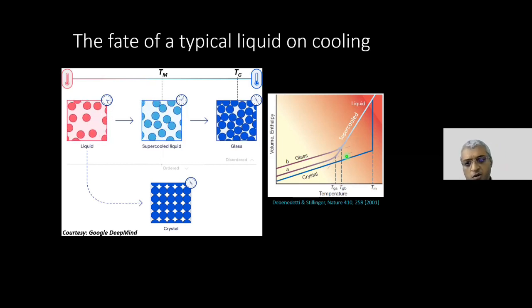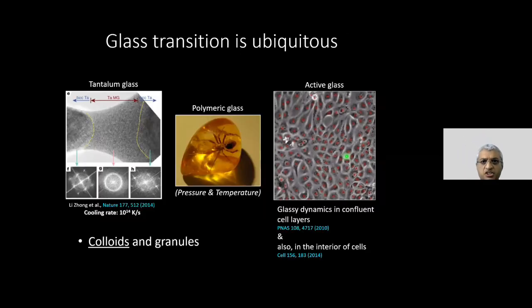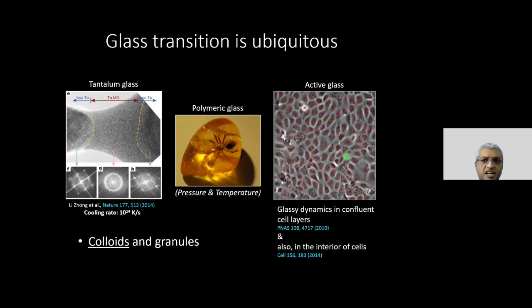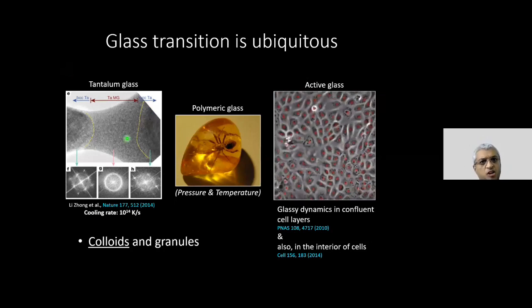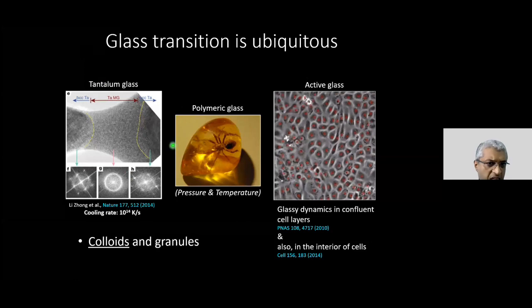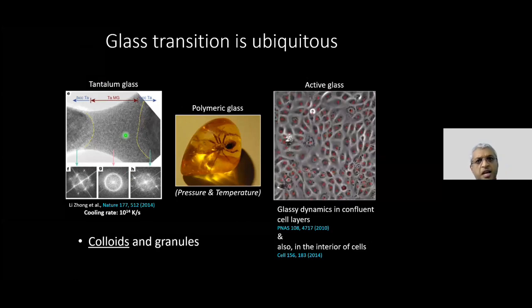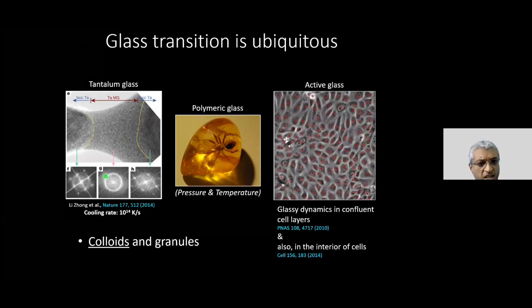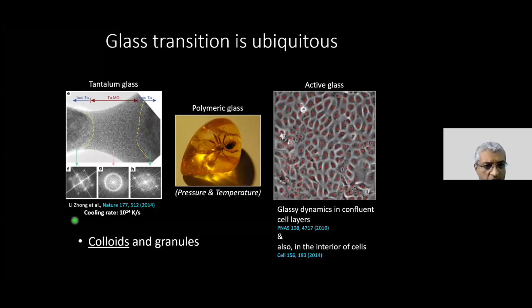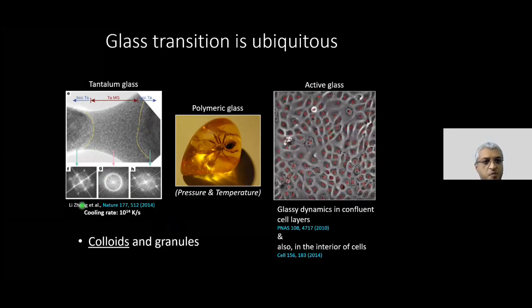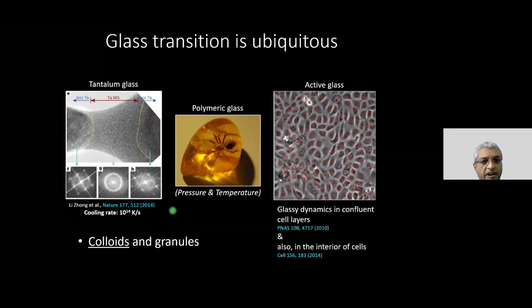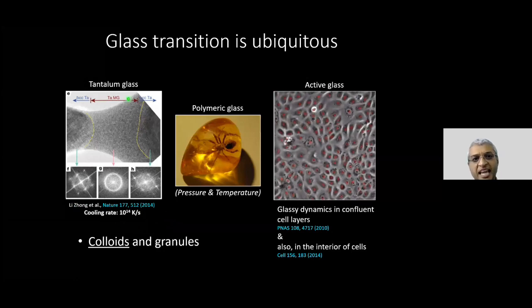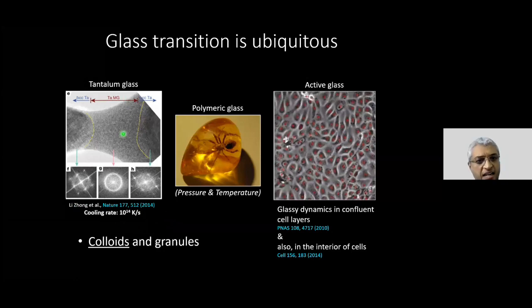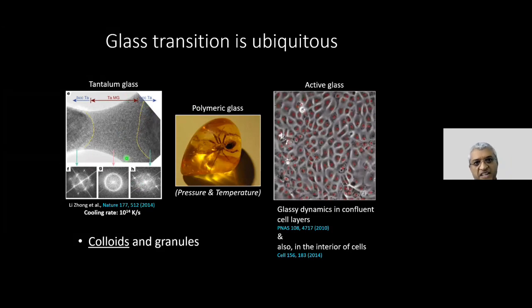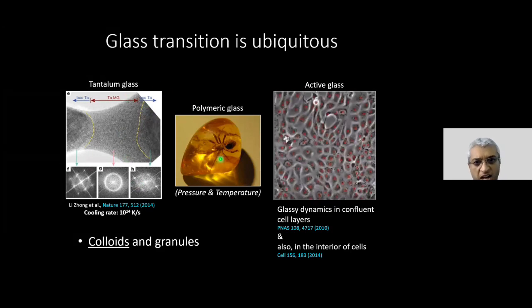Now, what's spectacular about the glass transition problem, of course, is the number of different materials that we know undergo this transition. For example, this is glass made of a pure metal, tantalum. And what I would like to draw your attention to is they have experimentally managed to get this cooling rate. It's 10 to the 14 Kelvin per second. So if you can do that, you can even drive a single component metal into a glass.